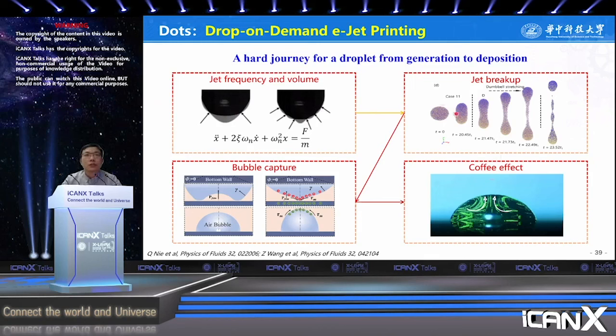And as shown in the top right figure, the flying jet has a high density of charge. When the charge density exceeds a critical value, the jet may break up into two drops or more satellite drops. These drops are harmful in printing. When a drop deposits on a substrate, as shown in the bottom left figure, it is easy to contain an air bubble in the center.